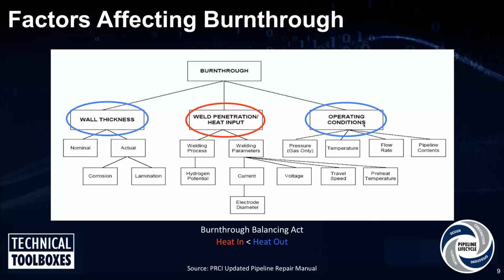So when you get to in-service welding applications, and you go talk to your in-service welder, it's very important that you clarify what welding heat input means, and that it's not just your welding current. It's a relationship primarily of the current, voltage and travel speed, but it's primarily controlled by the current and the travel speed. So typically when you're dealing with in-service welding, you want to control that welding heat input by controlling that welder's welding current range and his travel speed range. So it's two factors, it's not just the current. But from the welder standpoint, he always just refers back to the heat, which is just the welding current.